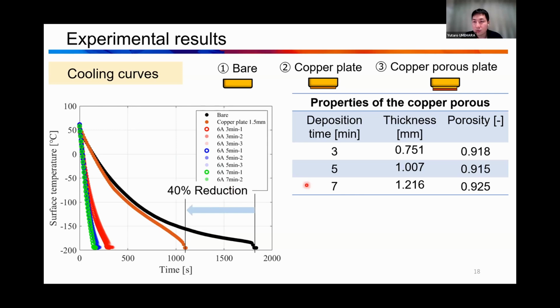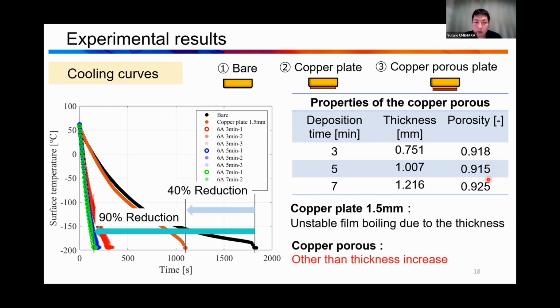Then we added the different copper porous plates, like this. We changed the deposition time to make the copper porous plate: 3 minutes, 5 minutes and 7 minutes. When we increase the deposition time, the thickness also increases, but the porosity doesn't change much. This one is a very good result, and we can achieve a 90% reduction of the cooling time. In the copper plate case, maybe there is some effect to reduce the cooling time, unstable film boiling due to thickness. But in the copper porous case, the thickness is thinner than the copper plate, so maybe this effect is not so much. So maybe there is a different effect improving the cooling characteristics.